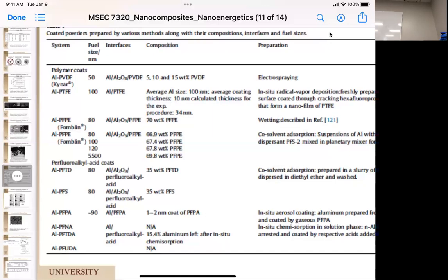Now, they also have a couple other ones. Most of them use the PTFE or polyvinylidene fluoride (PVDF), but they can also use perfluoroalkyl carboxylic acids. So those are the things they used to do the Teflon coating on pans. They would do the carboxylic acids right here. And so that's a nice way to do it because that self-adheres to the surface. And so it actually will help with the suspension, and that acts as your fluorine source as well. So there's a lot of different ways to incorporate solid fluorine oxidizer into your system where you don't have to worry about the actual reactivity of the fluorine itself.